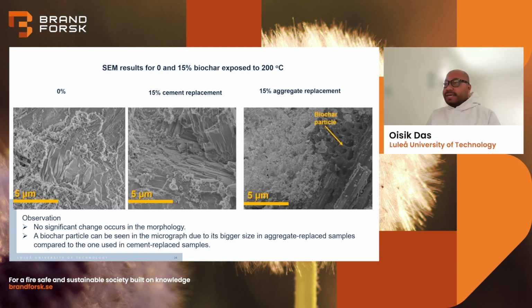And these are the same samples which were exposed to 200 degrees centigrade. So we see that at 200, no significant changes in the morphology occur from room temperature, 23 degrees centigrade. So same, again, for the 15% aggregate replacement, we see a biochar particle because the size of the biochar which was used to replace aggregate was way bigger compared to the fine biochar.